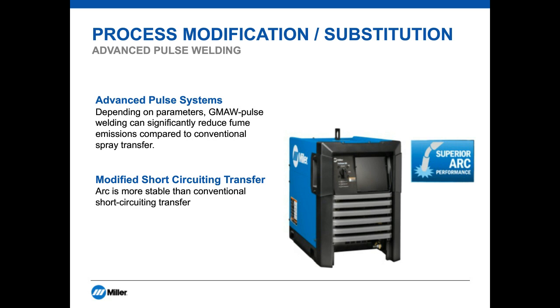Keep in mind, though, that a simple change to pulse may not result in the expected decrease in fume generation. You may need to optimize the welding parameters to get the desired results. You should contact your welding supplier if you need assistance. Also note that we do not typically see a similar reduction in fume when we use pulse transfer with flux and metal cored wires.